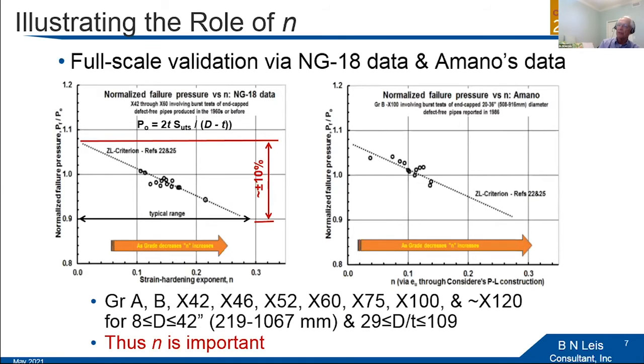Historically, failure criteria have used reference stresses that were very conservative, as was evident in the prior chart. The purpose of this chart is to illustrate the role of strain hardening exponent in regard to failure pressure. And we see on the ordinate here, in both cases, the same ordinate. It's a normalized failure pressure, where the pressure is normalized in the context of this normalization parameter, which includes the material UTS, the pipe diameter, and the pipe wall thickness. And what that allows us to do is then compare failure criteria for defect-free pipe.